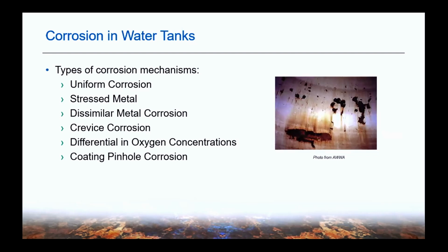It's my understanding that we also have some potable water or drinking water personnel on the phone today, so I wanted to make sure that we talked about corrosion in potable water. Speaking specifically to water tanks, there are some common types of corrosion that we see. In steel tanks, steel in and of itself is very irregular in its composition. So on that same steel plate, some areas may act as the anode and others may act as the cathode. If you don't properly mitigate this, if you don't put a barrier coating on it, if you don't employ cathodic protection and some of the other known techniques available to us, the result is corrosion attack that appears as random, closely spaced pits.